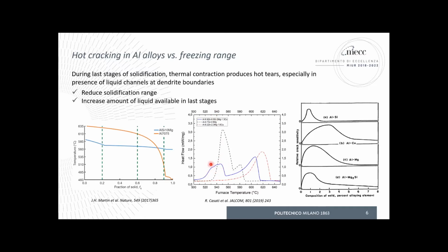We have backfilling of the crack. We have an excess of silicon, of eutectic, in the end of solidification that helps in removing all the cracks, or helps in avoiding formation of cracks. We got a very sound microstructure in the end of solidification.